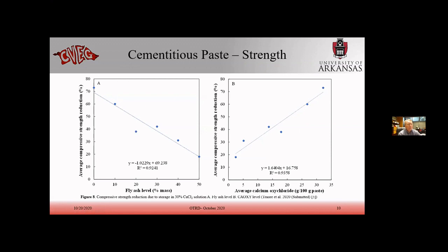These are 3 to 6 mortar cubes tested per age for each one. You can see that as we increase fly ash content, we see a decrease in the reduction in our compressive strength, so it's closer to what it originally was at 91 days of age. Even the 50% saw a little bit of reduction, about 20% after the 91 days in the salt solution.